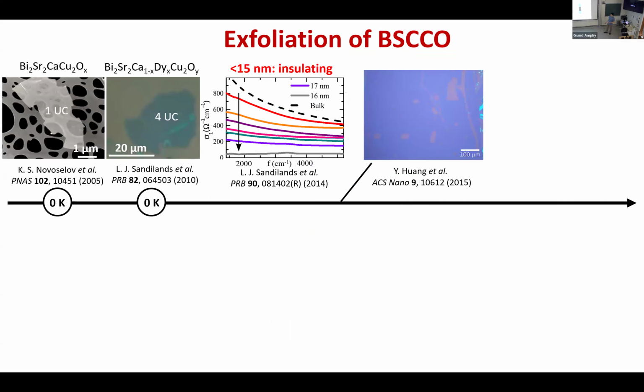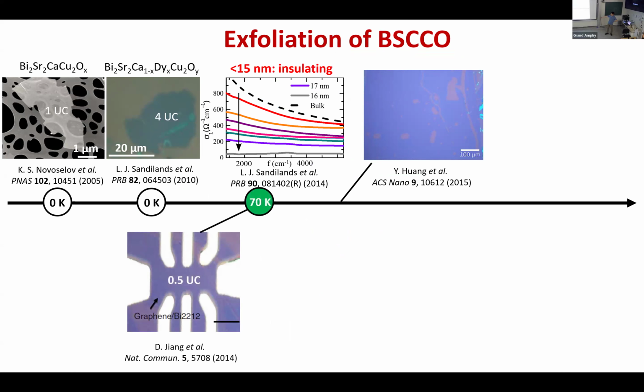Okay, cuprates. How many minutes can I have more? Maybe 10. Okay, so cuprates, the story is a bit complicated. Over the years, people tried to exfoliate cuprates down to a monolayer. Many of these studies couldn't see superconductivity in the monolayer. And then they tried to conduct this film. They can see superconductivity with transition temperature 70K.